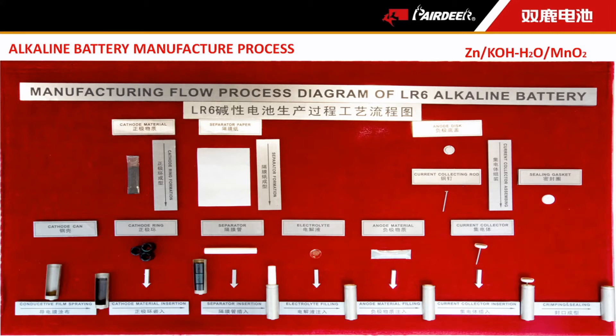Let us take the AA battery production procedure as an example. The procedure starts from the left side. The first step is to make three cathode rings made of manganese dioxide, carbon, graphite, and some adhesion agents. Then three cathode rings are inserted into the steel can. We insert a separator sheet through the cathode ring holes afterwards. Next, we put zinc paste inside the separator sheet. Finally, we put a current collector made of a nylon gasket and a carbon nail.